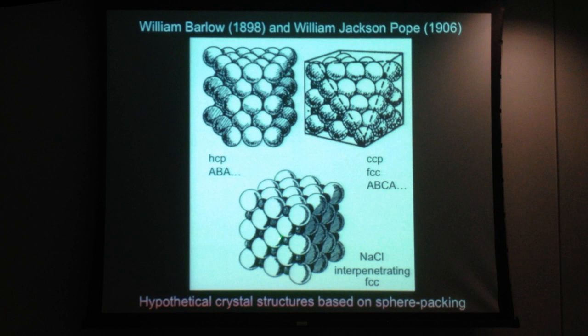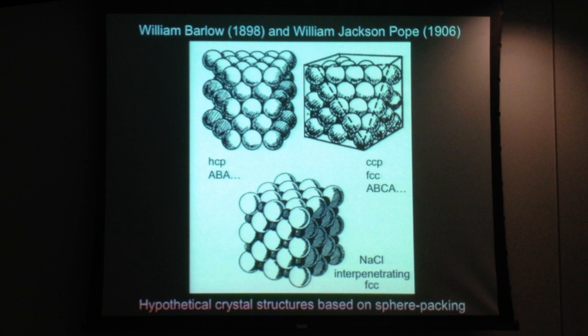So we have a look at the larger spheres. We have from here to here to here to here, that's a square. Or from here to here to here to here, a square. And then in the center of that face, yet another one. And if you look through the diagram, considering the dark spheres, the same result occurs. Here's a square face of the dark spheres, here to here to here to here, but then another one in the center of that face. So we have two face-centered cubic lattices, one of chloride ions, one of sodium ions, that interpenetrate one another.